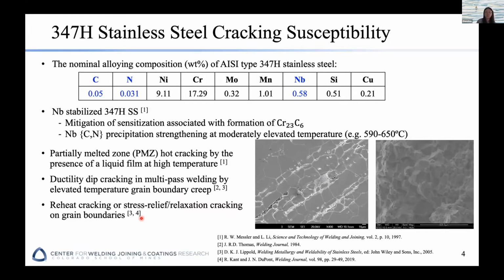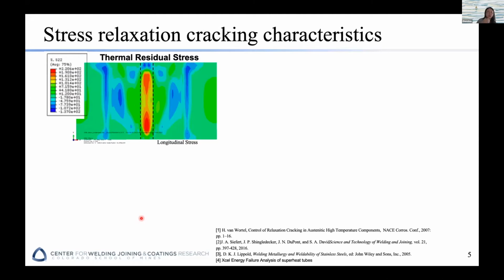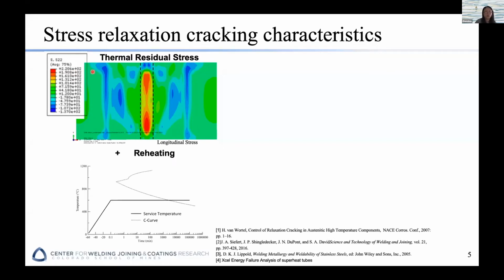That is known to be the cause for the cracking issue that is being observed in these welds. Okay, so first of all, we have to have residual stress. That is the number one factor that leads to the cracking issue. Okay, so this shows simulation results of the residual stress distribution after welding, and this center red region shows where the weld pass is. So you would expect a high tensile residual stress remaining in the material after the welding process.